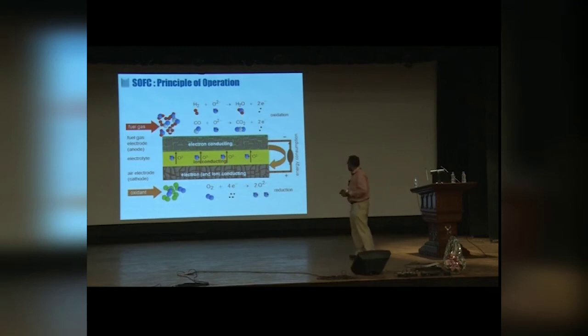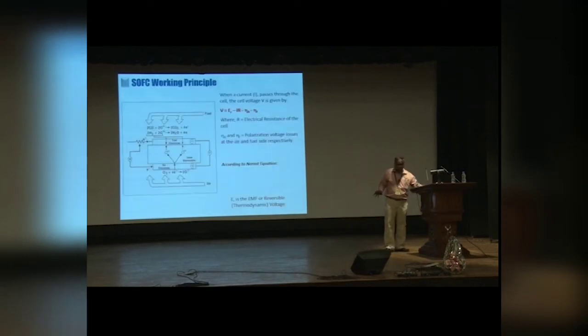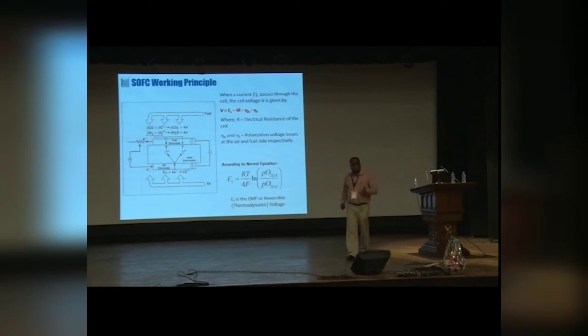And the other condition is that you must keep it at a particular temperature. At that temperature, oxygen ion can be produced. In our case, we keep it at 800 degrees centigrade, but from 700 to 800 degrees centigrade, you will always get some oxygen ion conduction. So why is it happening? Because of the Nernst equation.